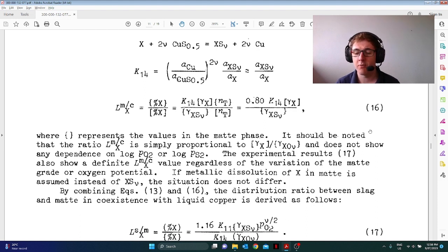So a lot of the fundamental research talks about PO2, but in industrial practice we talk about the product grades and product qualities. So when we're looking at matte smelting processes, nickel and copper, people talk about the matte grade, and in lead smelting, when you have a mixed bullion and slag system, people talk about the lead and slag, and other sorts of ratios there. So it all depends on what industrial process you have, all these different sorts of product qualities or targets.